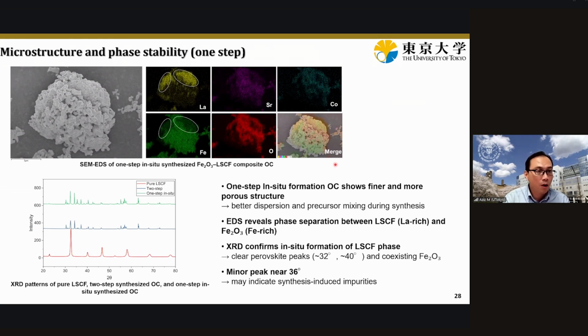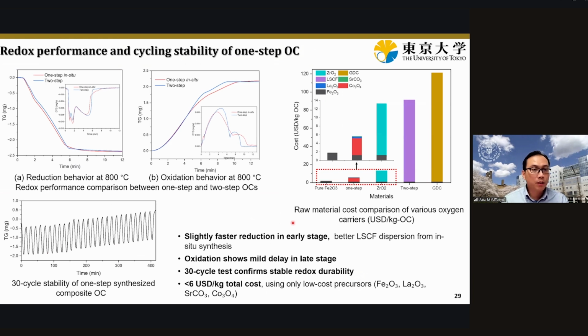And in some experiments we confirmed the existence of lanthanum, strontium, cobalt, and iron oxide. And then, okay, by doping or mixing with perovskite materials, we can have a much more stable performance of the oxygen carriers over the years.